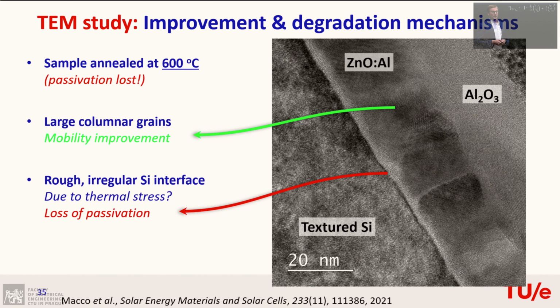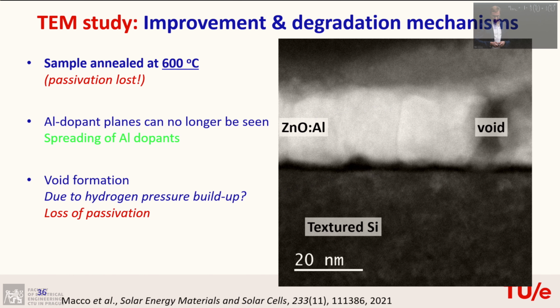What happens if you go too high with your annealing temperature, then you lose your passivation. And if we then look again over the microscope, I will see different things. So you see that you form actually large columnar grains over here. So the mobility of the carriers in those grains is probably improved, but at the same time you can lose your hydrogen. And there's also rough interfaces now over here. So this is probably due to thermal stress and not good for passivation. Also, we form even voids in your material, which you can imagine is just bad for passivation because you don't cover the whole surface anymore with your material. And this is due to maybe hydrogen buildup or pressure in your material that you don't want.